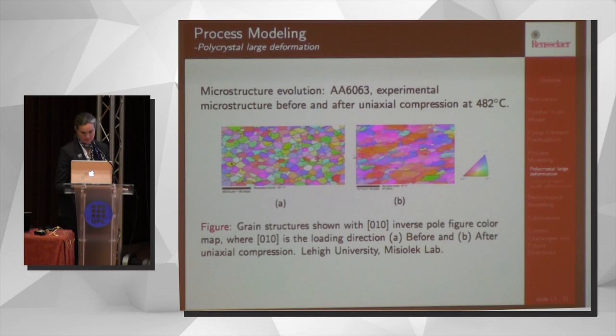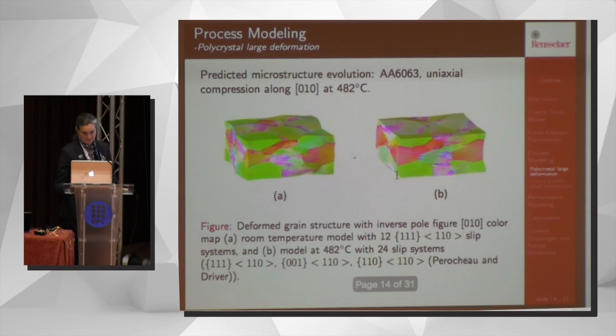And then after a compressive deformation, we see that the grains are becoming elongated because of the deformation. And we start to see some coloration variations within the grains due to misorientations, intragranular misorientations. And we also are seeing that certain colors are more predominant than other colors. And here's a simulation of a polycrystal. And so this was at 482 degrees C.